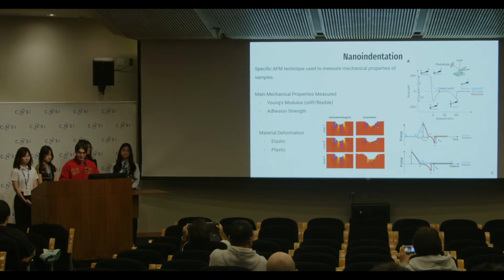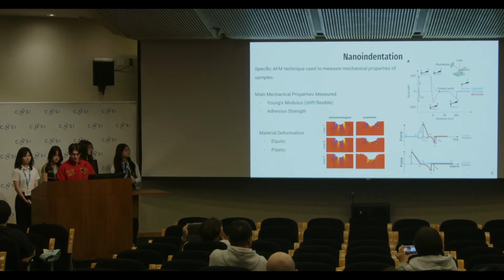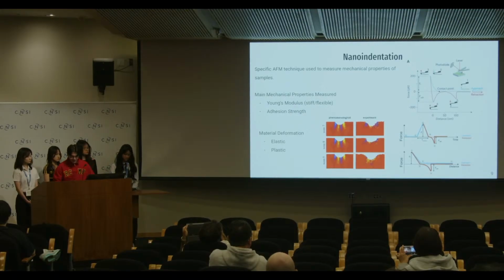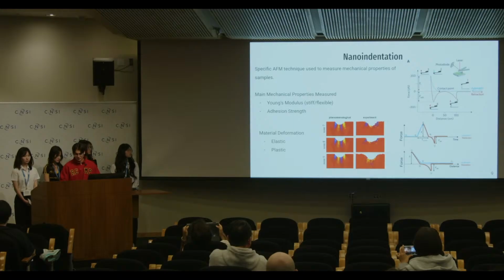And then probe 3 is when you start retracting the probe away from the sample, and that measures the adhesion. That's where you see the negative force here. And then on 4 and 5, it's also adhesion, but it's either non-specific interaction or a specific interaction.